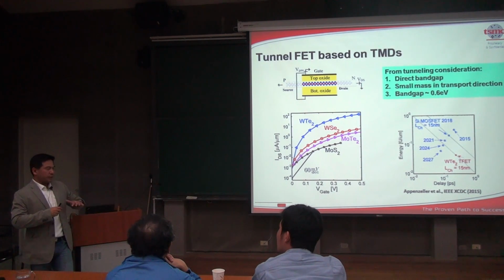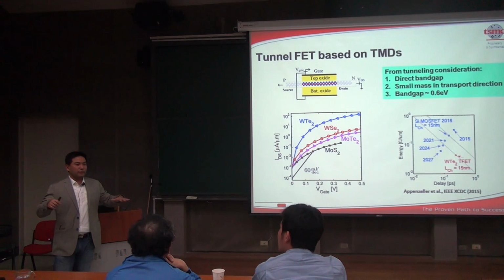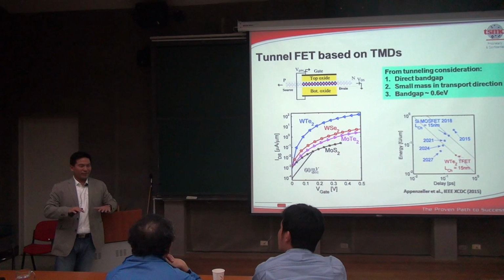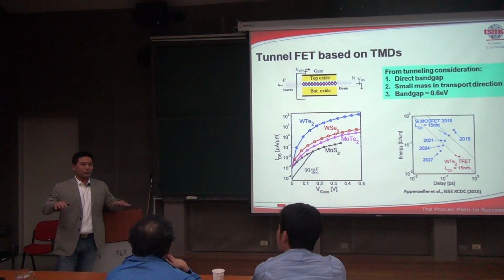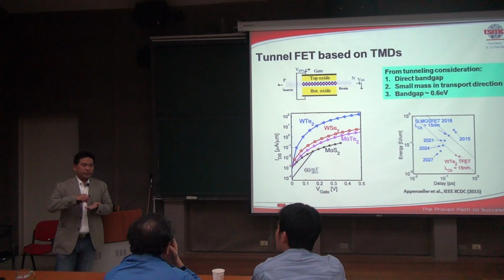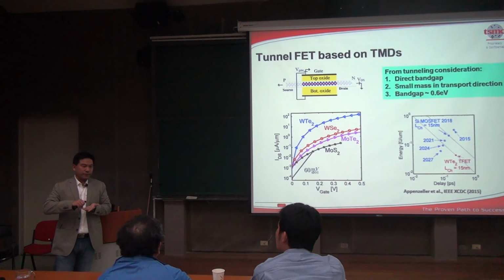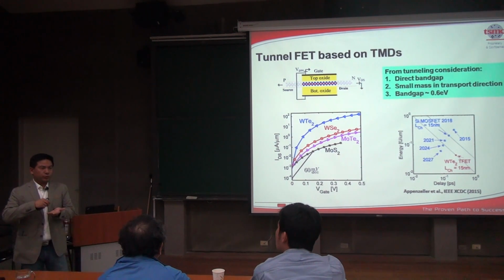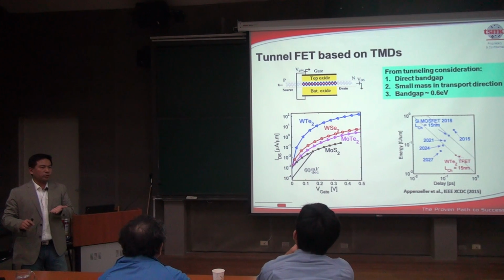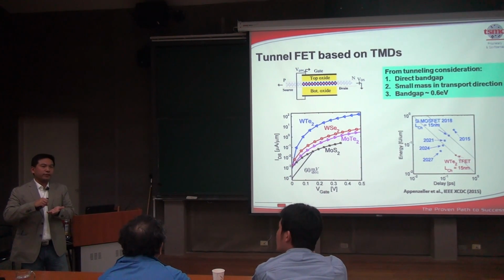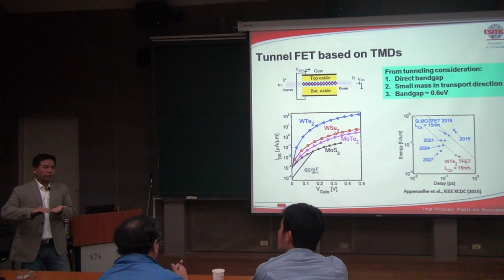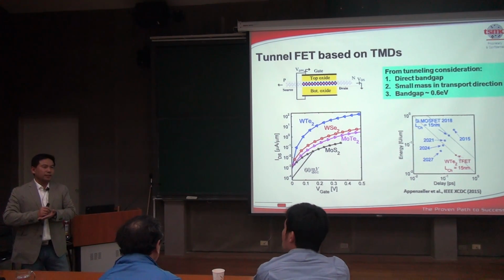So what usually happens is you have these 2D materials. Imagine that you sprinkle sesame seeds on these 2D materials. They would physically stay stable on the surface, and there are interactions between these molecules and the underlying 2D materials that either donate electrons or holes to the substrate. So it is like remote doping. The charge providing center is not in the lattice of the 2D material. It's actually in the vicinity of the material.